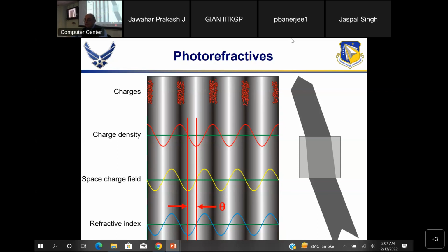And nowadays the bias voltages are reduced as well. But not down to 10 volts. It is still in the order of hundreds of volts. Hundreds of volts per delta. The delta n is actually typically not 0.1, it's probably 10 to the minus 3.